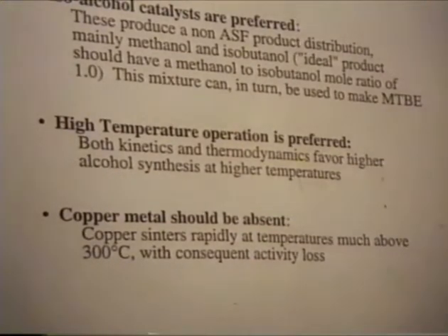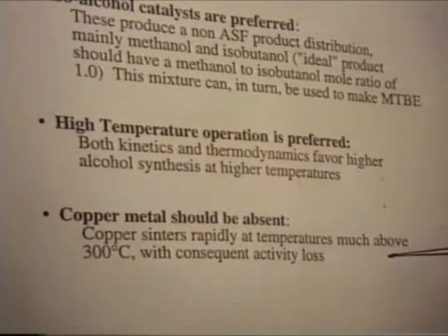Because we want to go to higher temperatures, we are not going to have copper metal present, because copper metal will sinter and deactivate quite rapidly above 300 degrees centigrade. So the formulations I'm going to talk about for the rest of the talk do not contain copper.